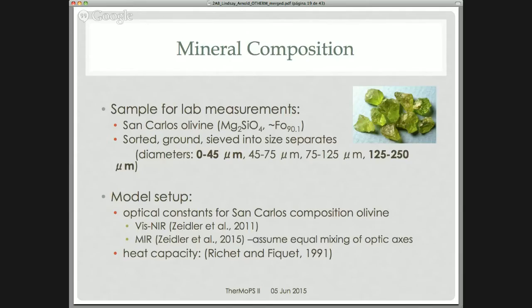Okay, so how do we enter mineral composition into the model? We put in optical constants for the relevant composition and also heat capacity. And for the sample that we decided on, Carrie had some San Carlos olivine that was available to grind and sieve, and I pulled a random internet picture that looked very similar to ours. So we sorted this in sieve to different size separates, but we've only had a chance to measure the size separates in bold, so the smallest and the largest, just to give us a rough idea of how our model is doing.